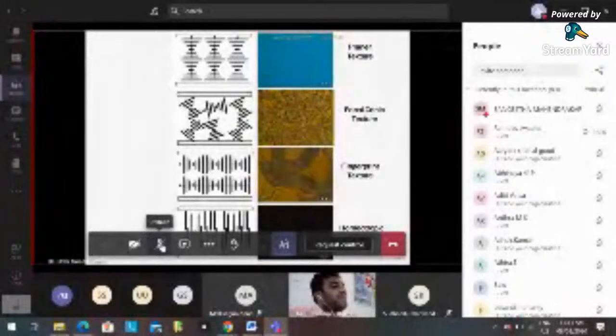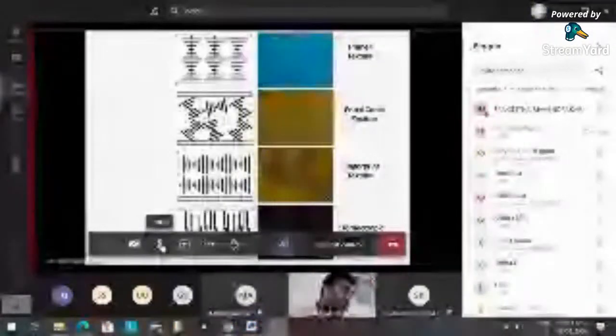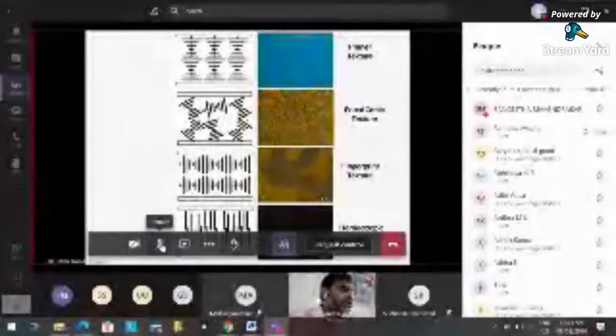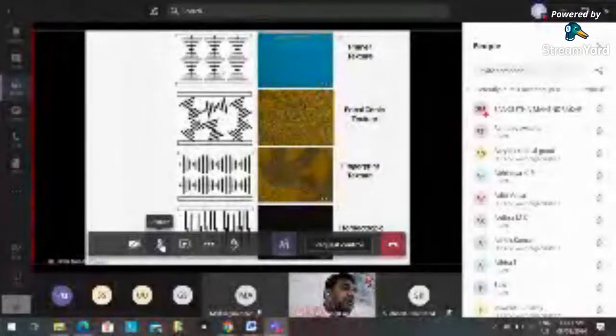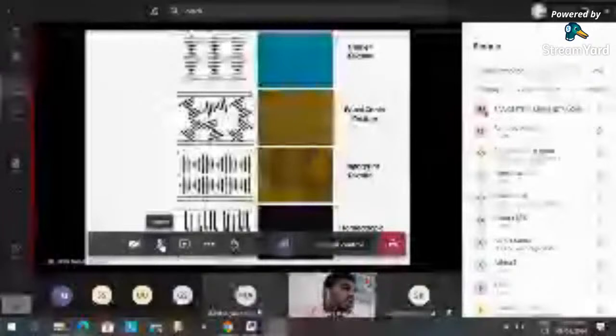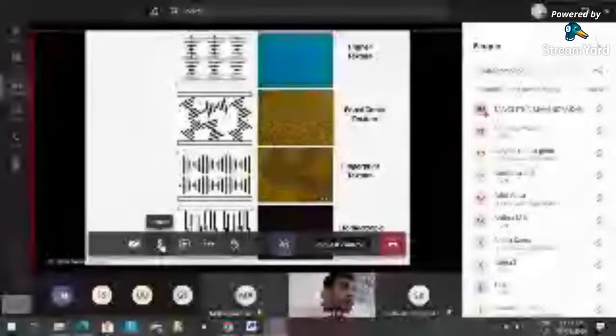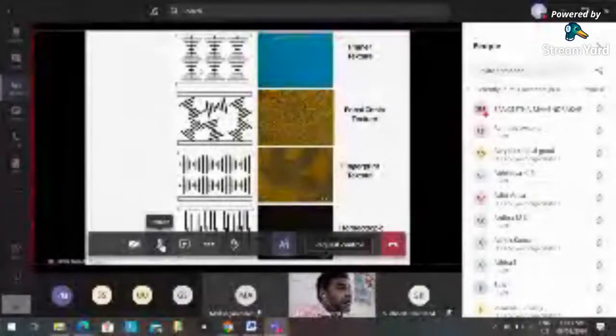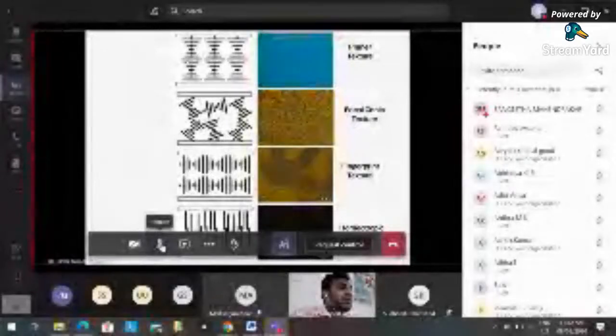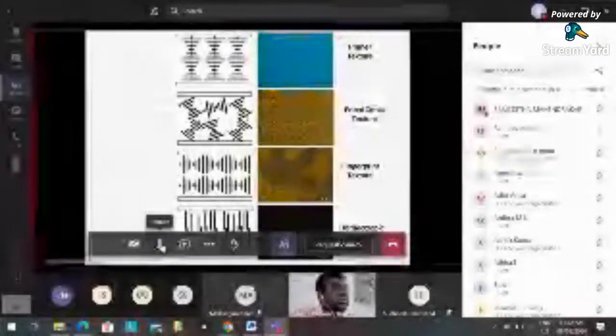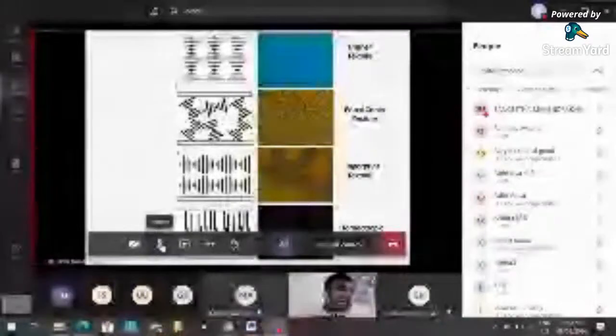Now there is again surface alignment, some kind of surface alignment, which plays an important role in the displays of liquid crystals. If the alignment is along this side, we can generate this alignment in the laboratory also, because these are very sensitive materials, and we can generate this alignment with the help of some surface anchoring. In the first case, all the molecules are aligned in a particular layer type structure. This will give planar alignment, and here they are randomly distributed. There is no alignment, so we get a focal conic texture here, and here is the fingerprint texture.